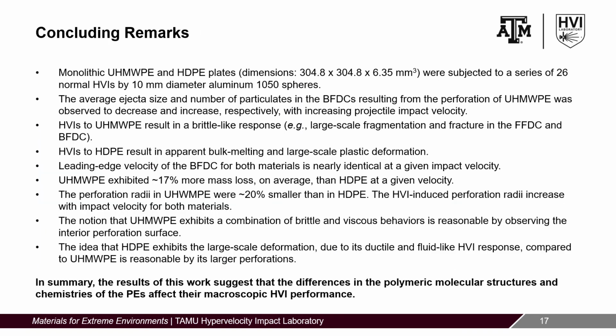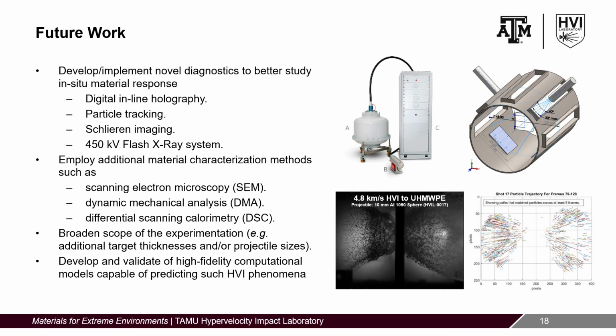In conclusion, ultra-high molecular weight polyethylene exhibits a brittle-like response, while high-density polyethylene exhibits apparent bulk melting. While the backface debris cloud velocities are similar for the two materials, ultra-high molecular weight polyethylene exhibits approximately 17% more mass loss on average than high-density polyethylene. Also, the perforation radii are larger in high-density polyethylene than ultra-high molecular weight polyethylene. This work serves as a foundation for comparing these two polyethylene materials.